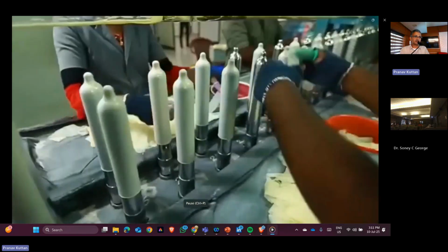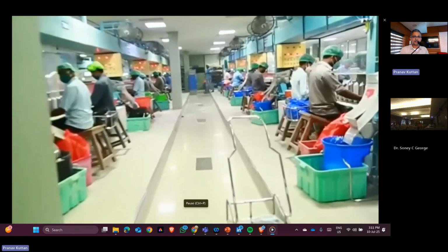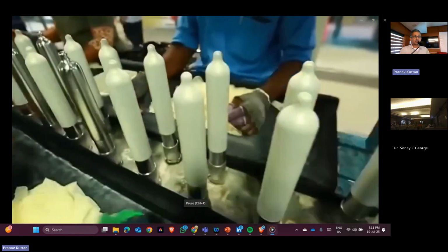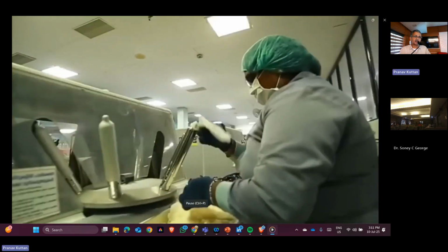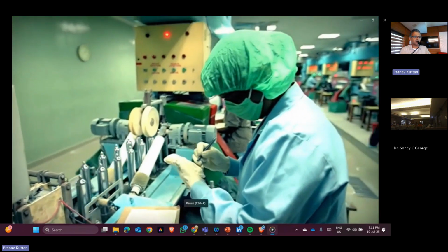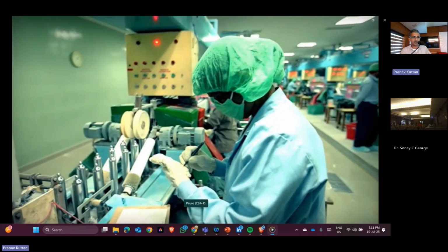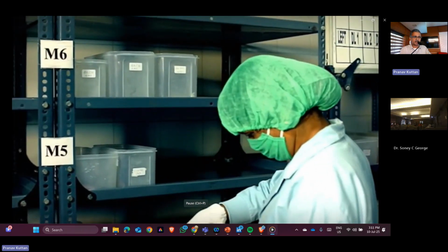100% testing is done, where this is being tested using electric current of specific voltage and amperage, and then this is being rolled, and taken into the packing division where it is packed in a single pack using silicone oil as the lubricant in aluminum foil, and then this is being secondary packed in boxes, and it is going for the dispatch.